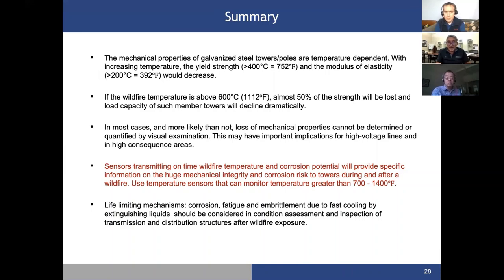Once you identify those structures, you should look at the corrosion fatigue and embrittlement if they are exposed to extinguishing liquids that can cause specific phase transformations that result in embrittlement. In short, we need to pay attention to the condition of these structures after exposure to wildfire because they may be at high unacceptable risk.